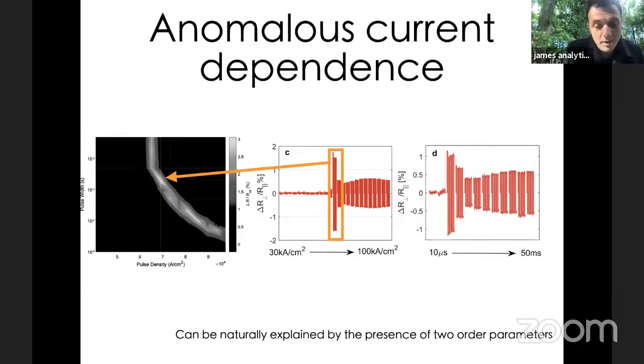Why would this be? Well, we think maybe the results of Shan Wu and Bob Buhrman might help explain this also. If we have two order parameters simultaneously present, one going in one direction and the other switching in the other direction, then what you're seeing here is probably just the addition of the two. So a large increase when one turns on at the threshold current, and then suppressed by the coexisting other order parameter, which is going in the other direction. So this might be a natural way to explain this bizarre current dependence too.